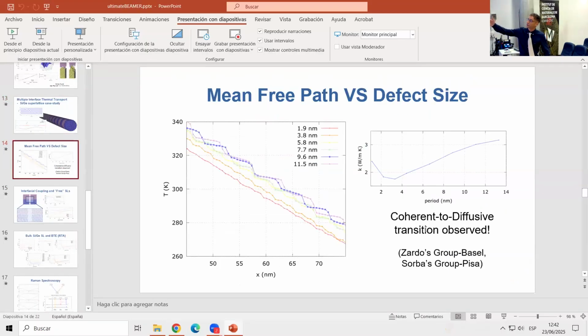So if here you could repeat the simulation at different temperature, this would change the mean free path of the phonon, and this would change the position of the minima. Because phonons, if their mean free path becomes shorter and shorter, they would become able to experience the sequence of interfaces, even if the period is smaller and smaller. And the converse is also true.